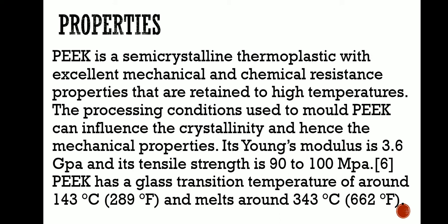PEEK is a semi-crystalline thermoplastic with excellent mechanical and chemical resistance, properties that are retained to high temperatures. The processing conditions used to mold PEEK can influence the crystallinity and hence the mechanical properties. Its Young's modulus is 3.6 GPa and its tensile strength is 90 to 100 MPa. PEEK has a glass transition temperature of around 143 degrees Celsius, that is 289 degrees Fahrenheit, and melts around 343 degrees Celsius, that is 662 degrees Fahrenheit.